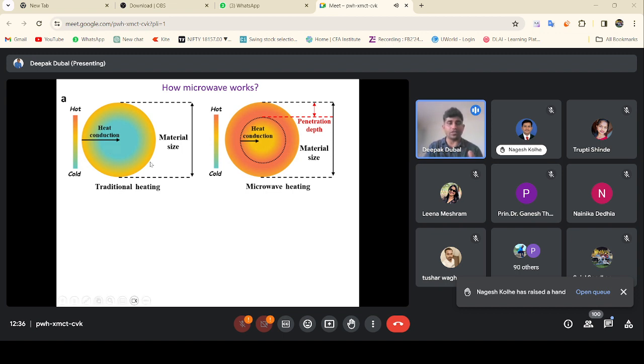This is the traditional heating. In the conventional furnaces, we pass electricity to the coil, then the coil heats up and transfers heat to the environment, then the environment heats up and passes the energy or heat to the sample. This is what we call the convection process, and through the convection process the heating rate is very slow, somewhere around 5 degrees per minute to 10 degrees per minute. But the microwave works totally opposite. The microwave directly attacks the sample. The sample absorbs the microwave and generates heat by itself, so it's not convection heat. Because of that, the heating rate is almost 50 degrees per minute to 100 degrees per minute.